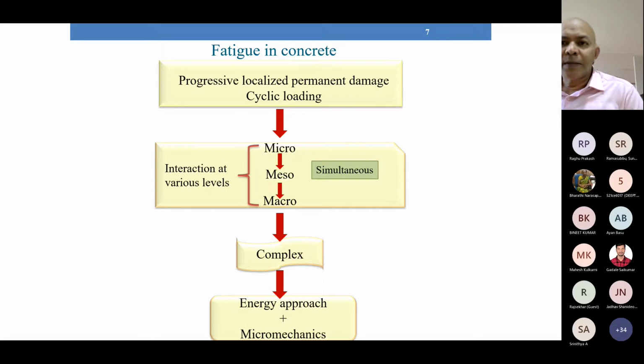So fatigue in concrete is basically a progressive, localized, permanent damage which takes place due to cyclic loading. More importantly, there are interactions taking place at different levels, the micro, meso, and macro, because we have the cement paste at a very small micro scale, the fine aggregate like sand, and at the meso scale, large aggregates. So the interactions are taking place at different scales simultaneously. The process is quite complex, and an energy approach would be the most ideal to describe it.